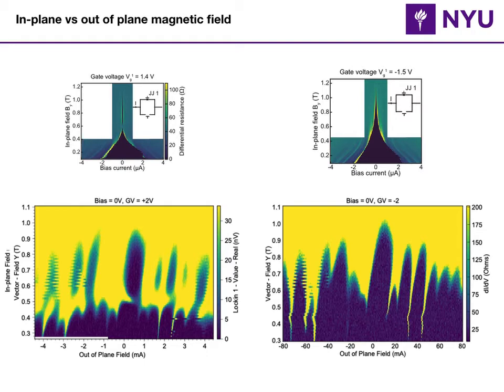One other axis I can show you is that if I park at zero bias and sweep the in-plane field, the x-axis is the same, but on the y-axis I now look at the out-of-plane magnetic field. That would be like the Fraunhofer pattern versus the in-plane field, right? As you see on the right side, where there is no transition, you see these patterns going all the way, and they're so straight that you can see there is no misalignment in the field. On the left side, you can see that there is an abrupt transition when you get to around 0.6 Tesla. And that is also showing up in the bias data.